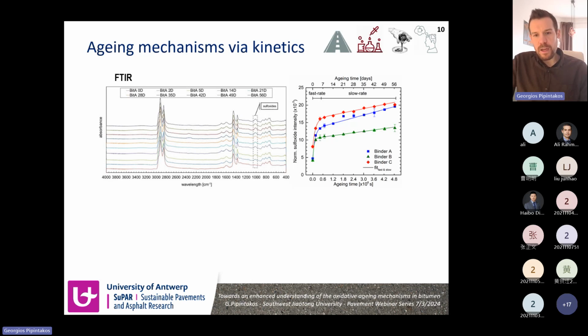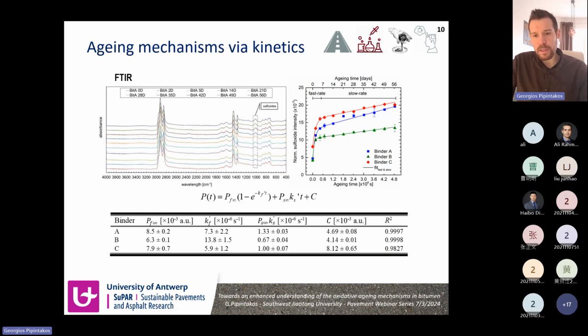So around 8 days, we have completed the fast rate phase, independent of the bitumen source, bitumen type or distillation that we had for these three binders. And then for all of them, we observed a constant slope. These data points were then fitted with a first order model for oxidation kinetics, as you can see in the equation below. All of them fitted well, which also justified that from FTIR we can indeed confirm that there are two rate determining phases, namely a fast and a slow rate phase. Of course, the fitting factors are shown in the table at the bottom of this slide.